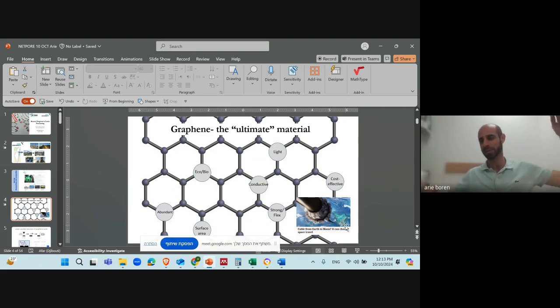At the beginning, we tried to order graphene from commercial suppliers. I don't want to mention names, but if you put it in XRD, if you put it in Raman, you see that it is not actually graphene. It is more like amorphous carbon, graphite. So we had to start making our own graphene. And one of the, I think, most promising methods to produce highly graphitized graphene with high quality and relatively easy is with laser.